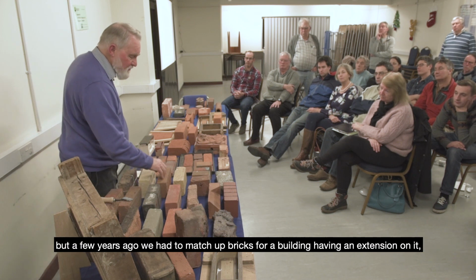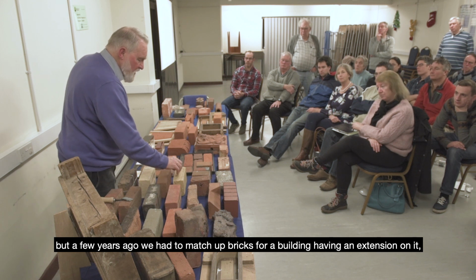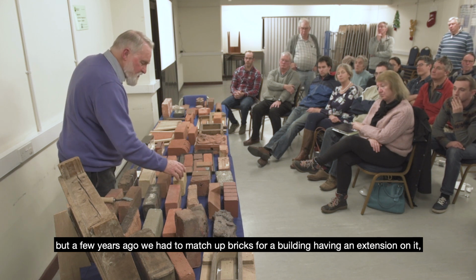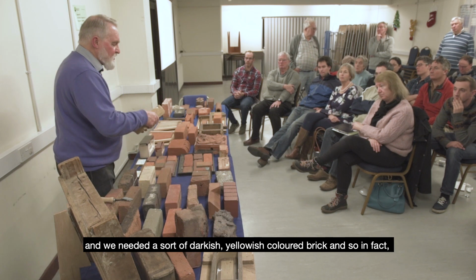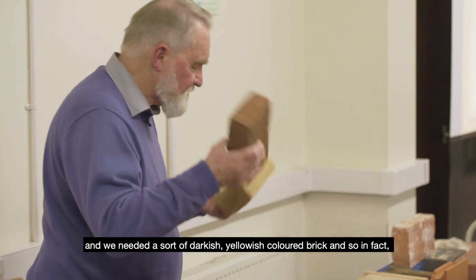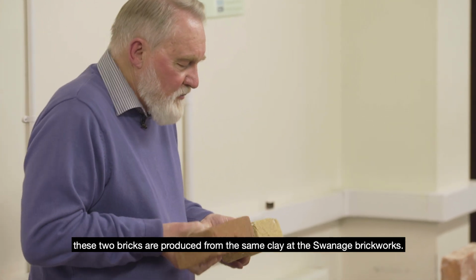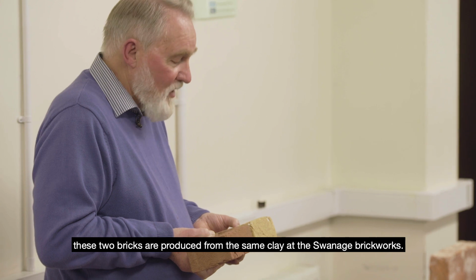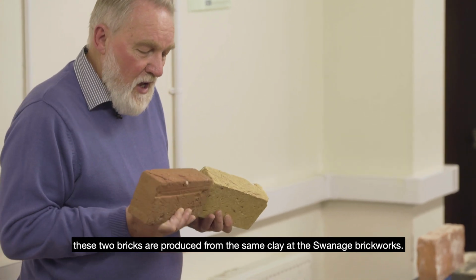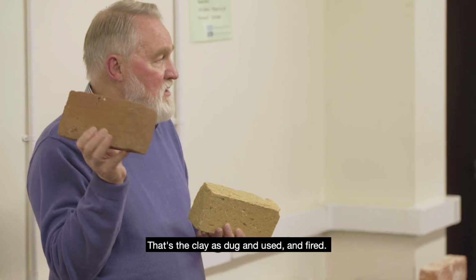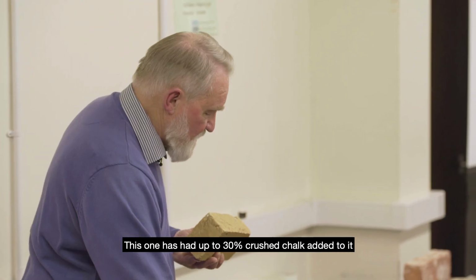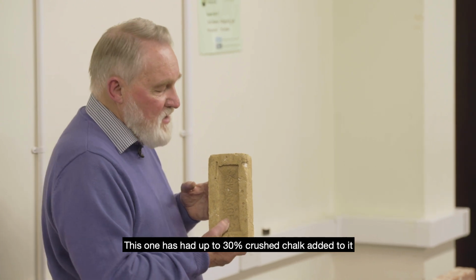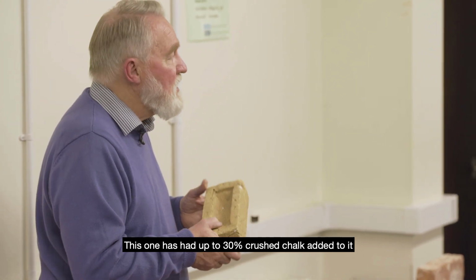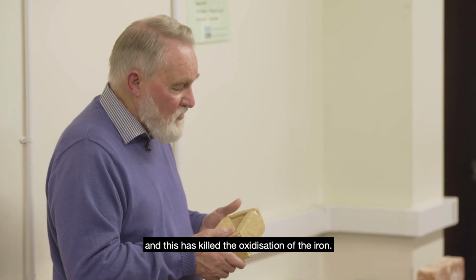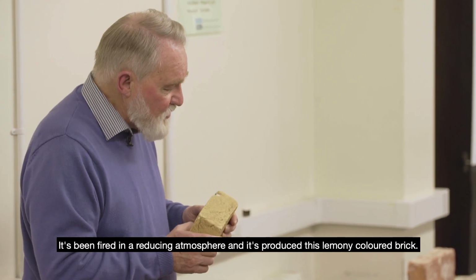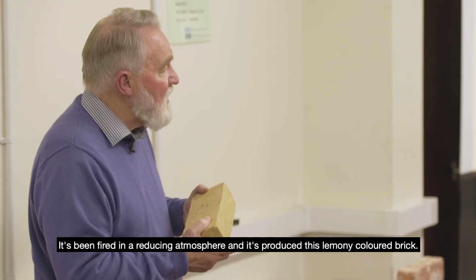a few years ago we had to match up bricks for a building and having an extension on it, and we needed a darkish yellowish coloured brick, and so in fact these two bricks are produced from the same clay at the Swanage Brickworks. That's the clay as dug and used and fired. This one has had up to 30% crushed chalk added to it, and this has killed the oxidisation of the iron. It's been fired in a reducing atmosphere and it's produced this sort of lemony coloured brick.